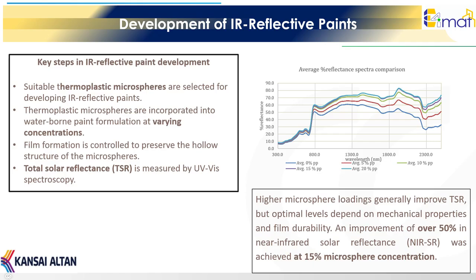Microsphere expansion produces a low-density microstructure, air-filled cavities with strong scattering ability, and increased reflectivity across visible and IR wavelengths. As can be seen in this graph, higher microsphere loadings generally improve TSR, but optimal levels depend on mechanical properties and film durability. In this case, the optimal level has been 15% loading of microspheres.